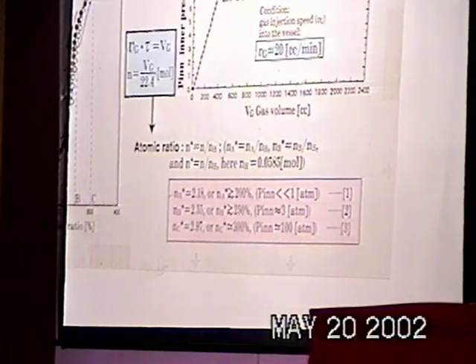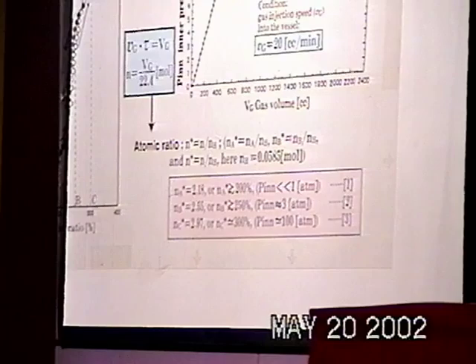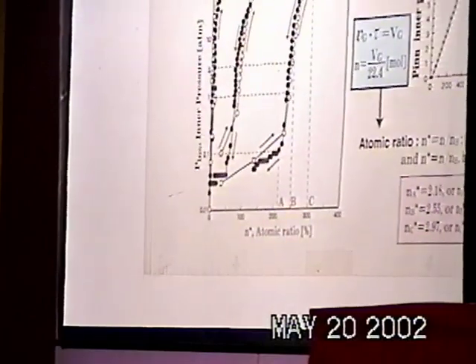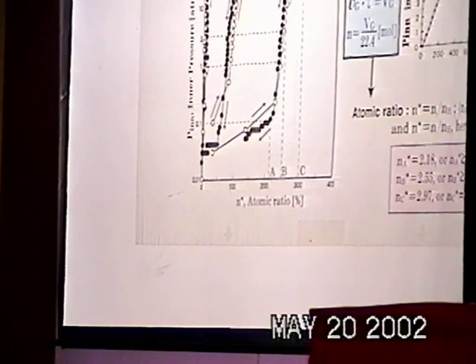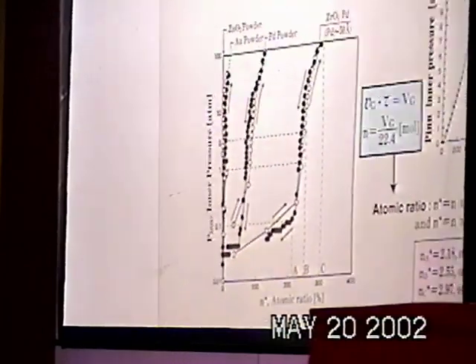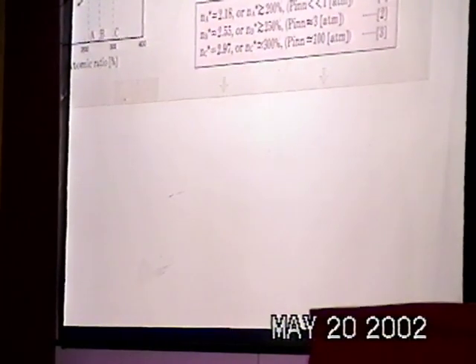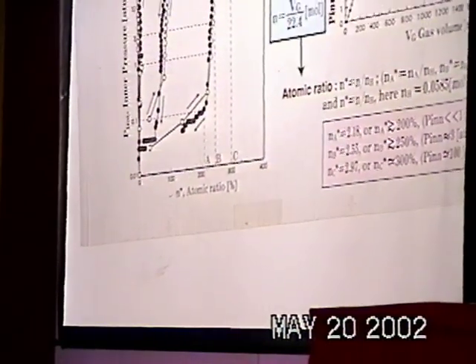Consequently, diagrams A, B, C, and D demonstrated that palladium atom clusters can be condensed with much deuterium. For instance, even under 0.1 atm, the absorbed atom density exceeded considerably 100%, and at 3 atm exceeded 250%. And also measured at 100 atm, it exceeded 300%. This slide, next slide please.